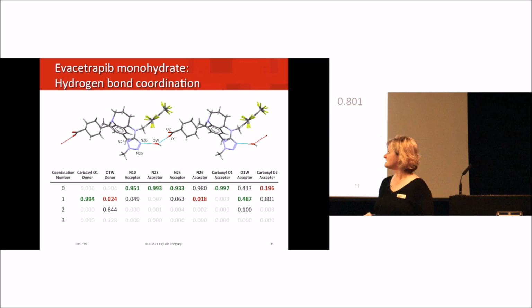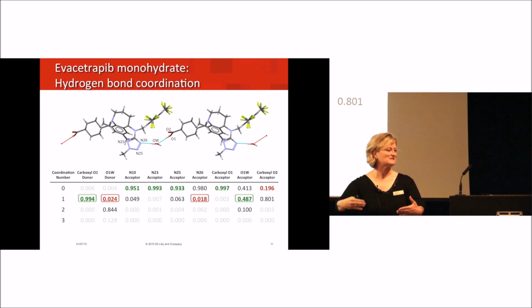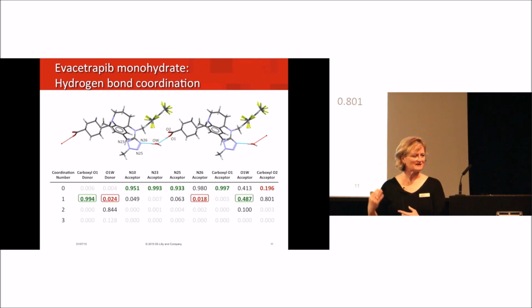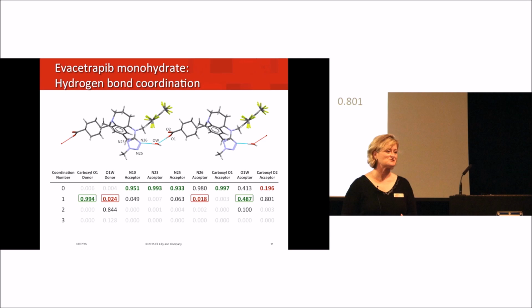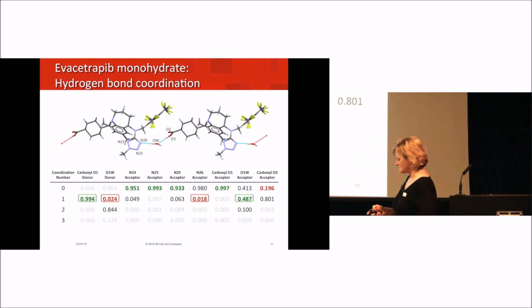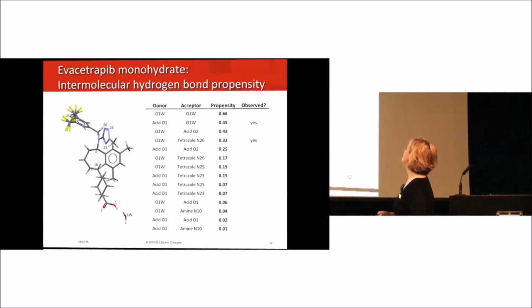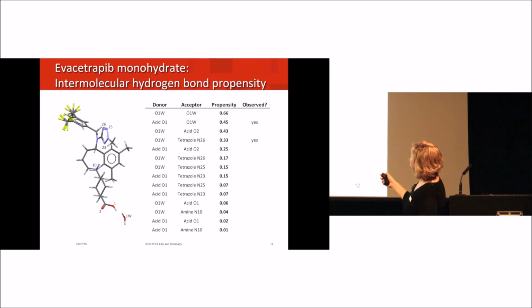And so if we look simply at the hydrogen bond coordination, and I'll step through a couple of these without going into the details of the numbers, what you can see is that there are a couple places where you have a lot of propensity, if you will, or coordination likelihood in this case being satisfied, but you also have a few instances where maybe things aren't so great. We didn't have this at the time we were doing this work, but certainly looking at this, it would have motivated us to continue our form screening. Nonetheless, we were motivated anyway, and it was a good thing. And I'll show you in a second.